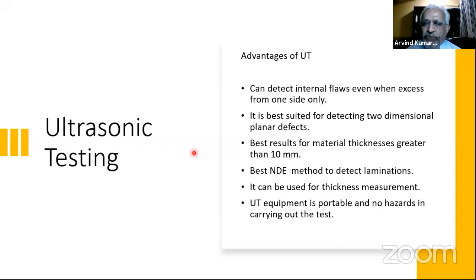But from the technique point of view, radiography, as I said, is giving you defects which are not so critical, but you are able to see well. But UT is giving you defects which are very, very critical from the service point of view, like lack of sidewall fusion. You will not detect it in radiography, but easily you can detect it in ultrasonic testing. Even tight cracks, which you may miss in radiography, you will be able to pick up in ultrasonic testing. So always place more confidence in ultrasonic testing with respect to radiography. Only thing is what needs to be controlled, we'll see later, so that we have more confidence.